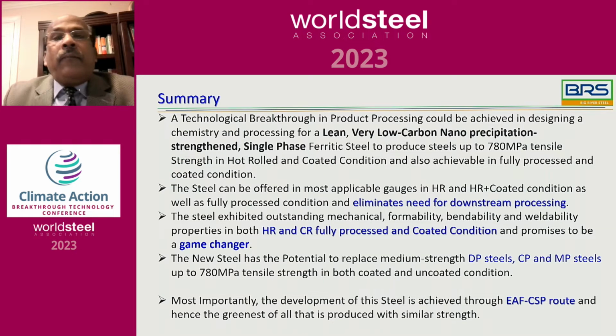In summary, this technological breakthrough in product and processing has been achieved by designing a chemistry and processing a very lean, very low carbon, nanoprecipitation strengthened single phase ferritic steel that can yield up to a tensile strength of 780 MPa in both hot roll and coated condition, and can also be achieved in fully processed and coated conditions. The steel can be offered in various applicable gauges in hot roll and coated condition, and it eliminates the need for any downstream processing.